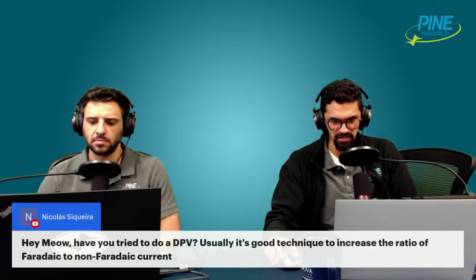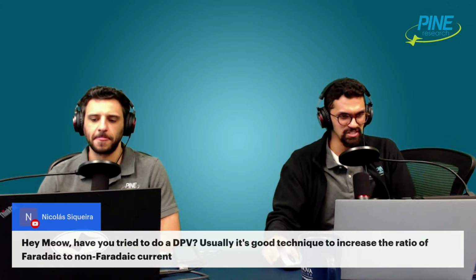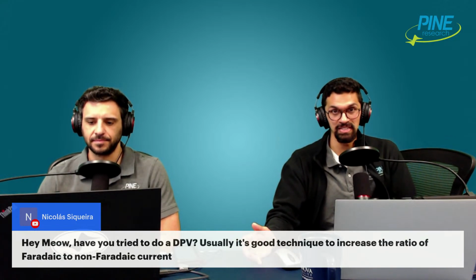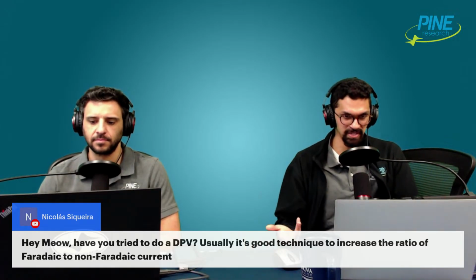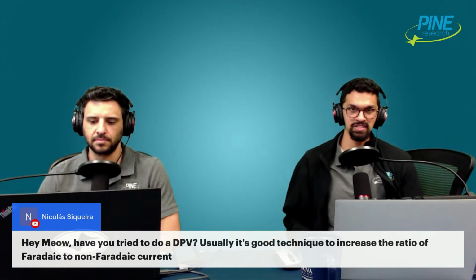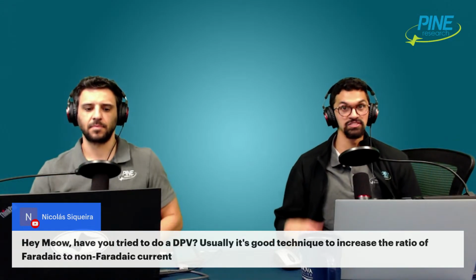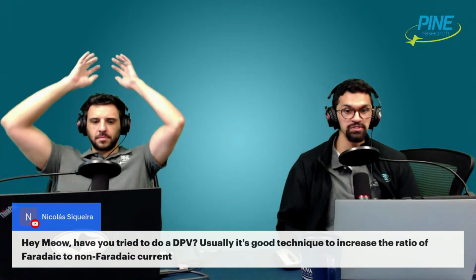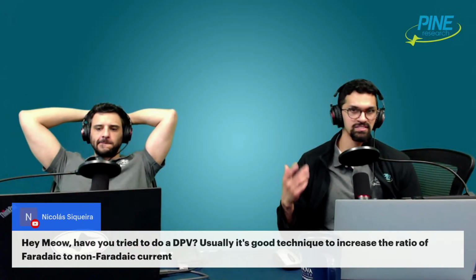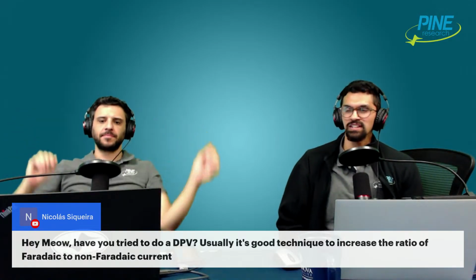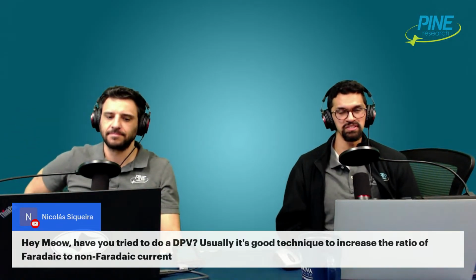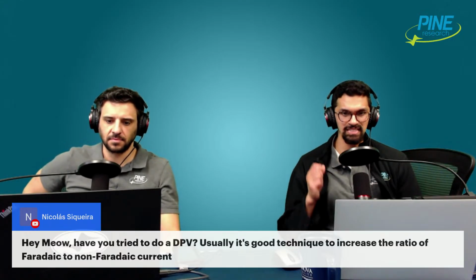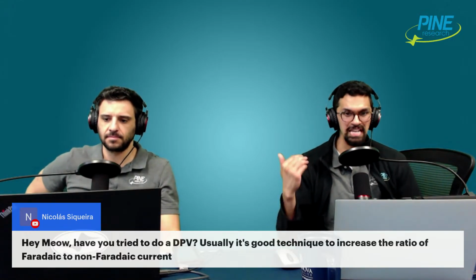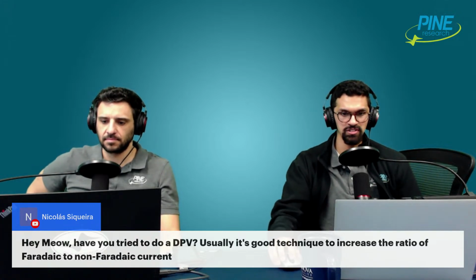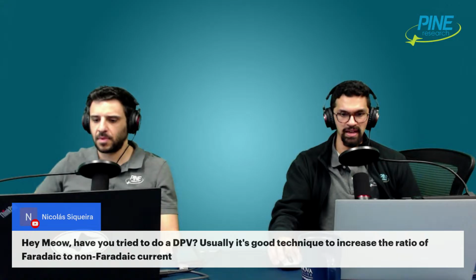And actually, Nicholas gave a very good recommendation, and it was actually going to be mine, which was to use differential pulse voltammetry, DPV. It is probably one of the best techniques for finding Faradaic currents under conditions where there's a lot of background current. Square wave or staircase is fine, but differential pulse is really very good at detecting very, very small Faradaic currents that are hidden or masked by background charging currents. So I'd recommend using that.